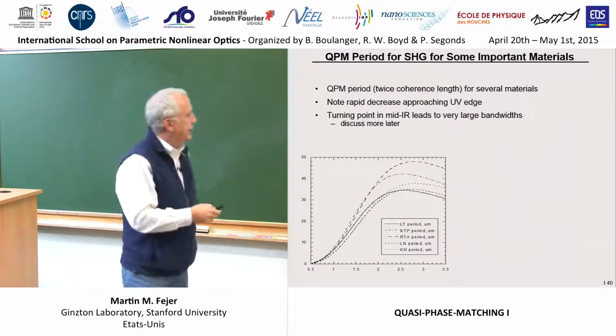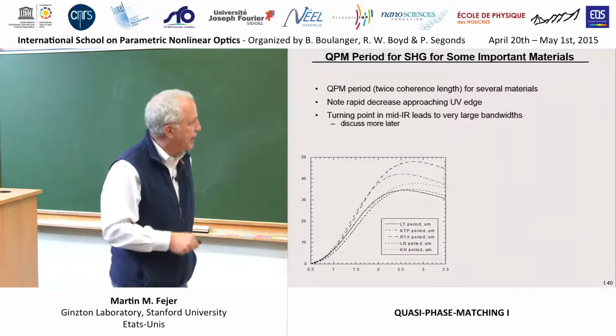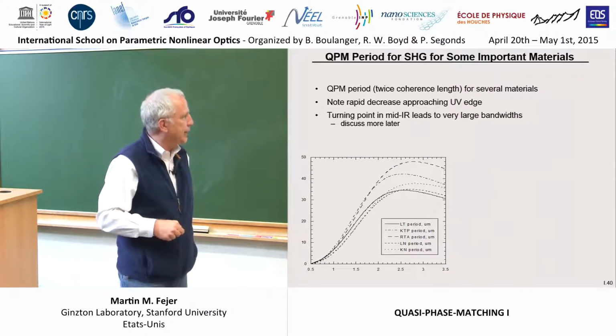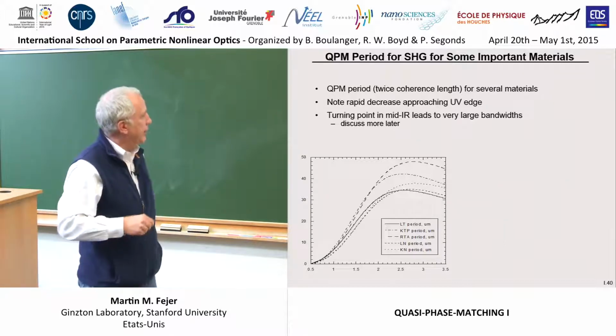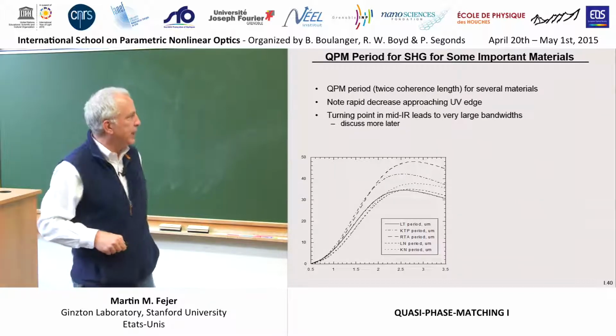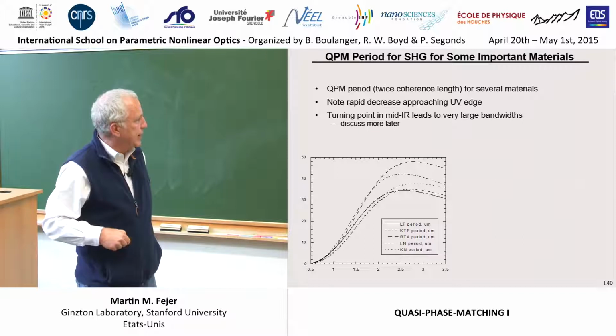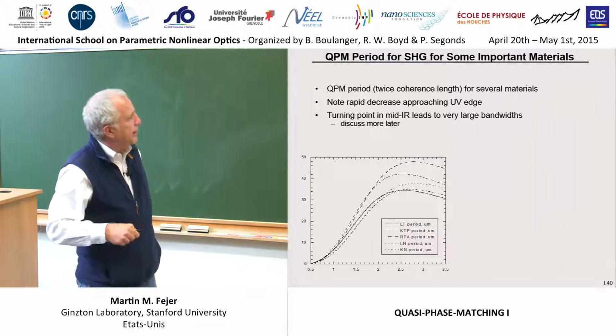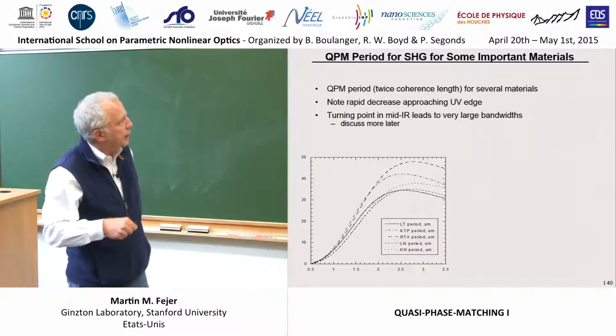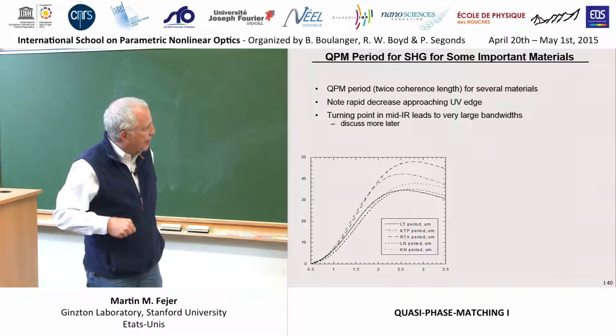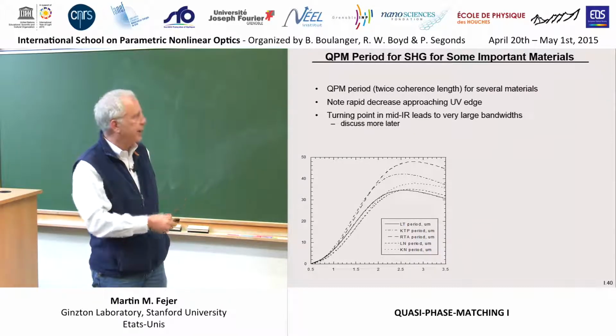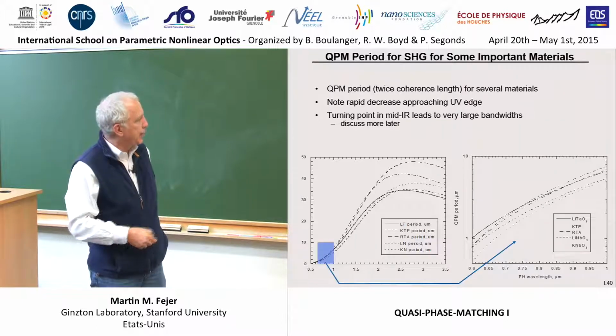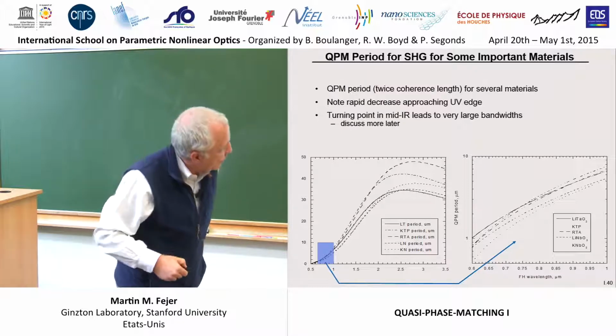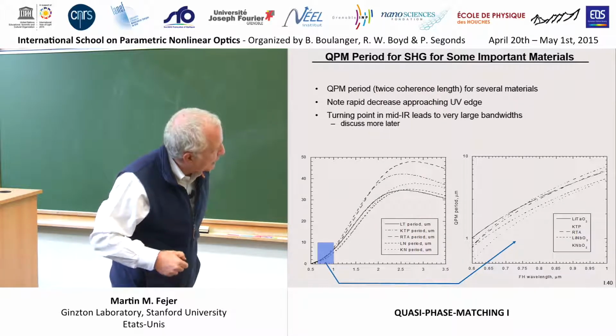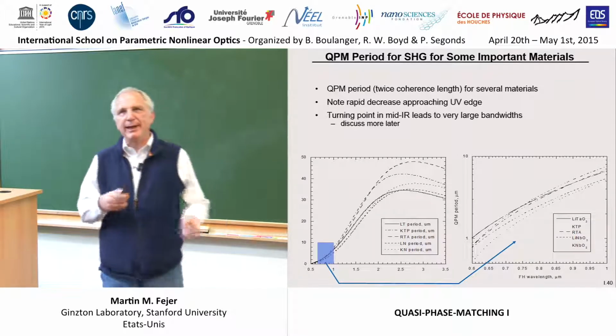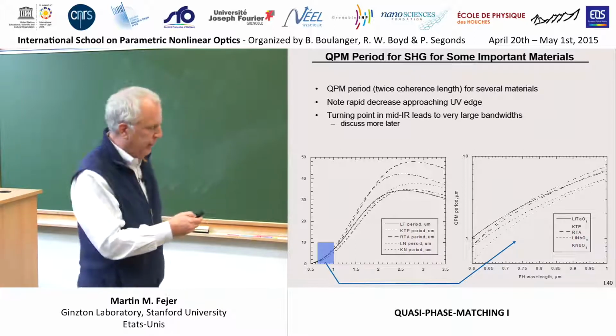Okay, so this is just a graph of some typical oxide ferroelectrics, lithium niobate, lithium tantalate, KTP. And this is the coherence length as a function of fundamental wavelength for SHG, ranging from 3.5 microns down to 0.5 micron. And you can see they're all more alike than different. In the infrared, 30 to 50 micron kind of coherence lengths. In the visible, they're getting down into these microns or approaching submicrons, which is often a challenge. If you blow up that piece in the visible, you can see now as we talk about doubling 1 micron or 0.8 microns, you're getting down to 1 or 2 micron coherence lengths, and that can be a technological challenge to fabricate. We'll talk a little more about that later.